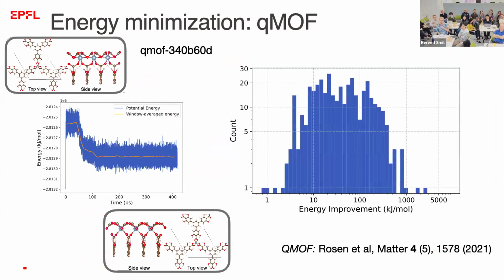Okay, so now a few interesting things you can do with this. Typically, what is done in these type of calculations is you do an energy minimization. You get, for example, the QMOF database, which is part of the Materials Project. They generate a structure and they optimize with DFT. And that is the starting point. So what we did is with the machine learning force field we trained, we follow the dynamics, and you suddenly see a phase transition. The reason was that all the hydrogen bonds rotated a little bit collectively, and that caused a much lower energy configuration.